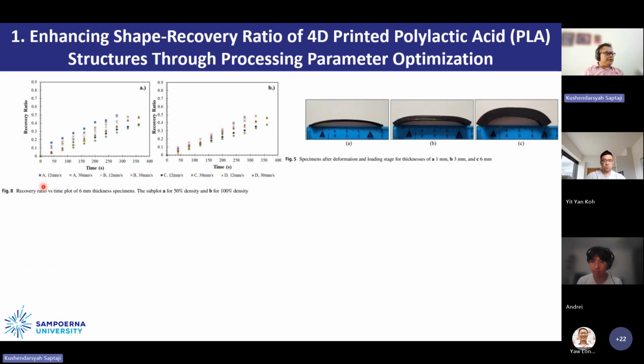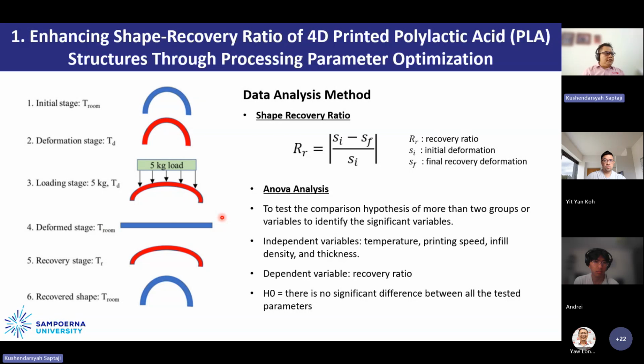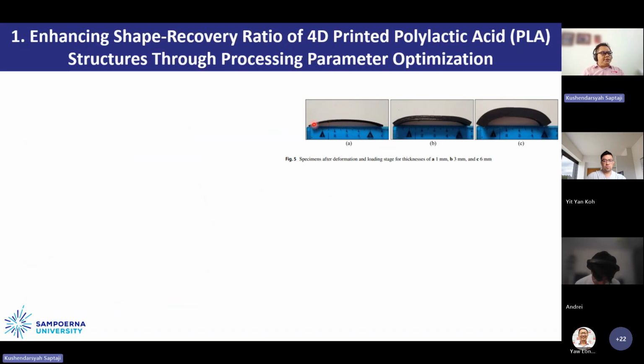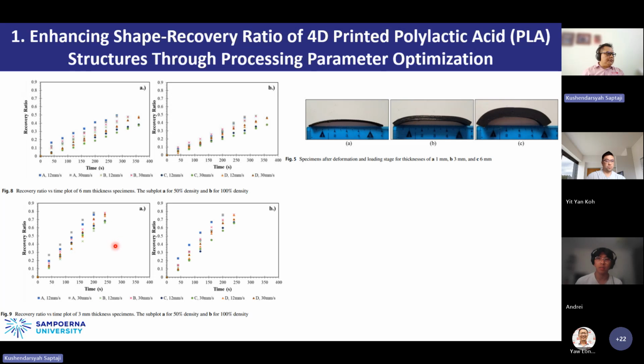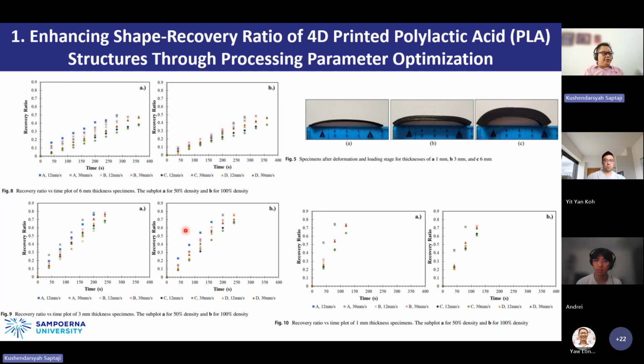So this is the plot showing the recovery ratio with respect to time. We measure at different times for different printing speeds. This is for the 50% density, this is for 100% density, and this is the specimen after the deformation and loading stage. So it will be like this. Not all samples are straight; there is still some curve in here. This is for the 3 millimeter thickness, this is for 6 millimeter thickness, and this is for 1 millimeter thickness. So we measure the recovery ratio for each time and each thickness and for different printing parameters.